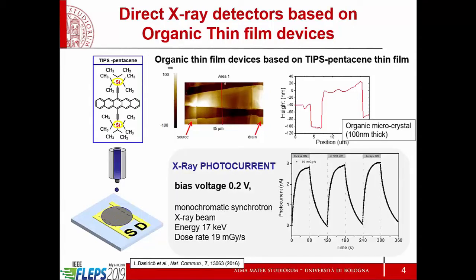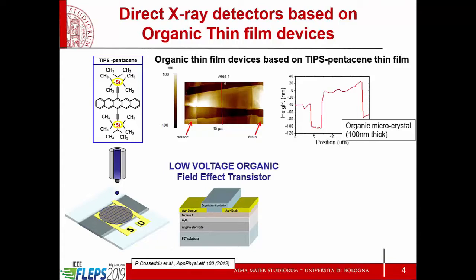And what is really interesting is that if you measure the photocurrent during an on-off switching X-ray beam, and the energy of the beam is the one typically used for mammography, so it's really a standard medical probe, you can get a very nice photocurrent induced with a bias voltage as low as 0.2 volts. That is very interesting, also because you can improve this result, of course. By the way, the response is linear and scales with the dose rate, and that is the very important feature that you need, and I will show you in a minute, to make a real dosimeter good for practical uses.